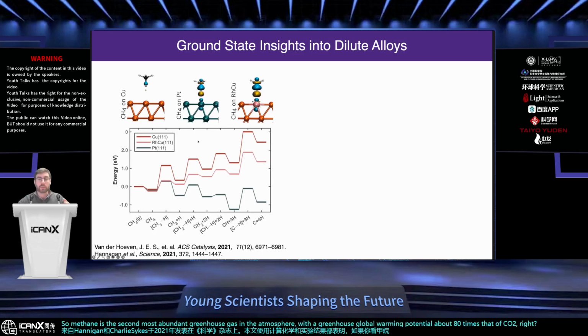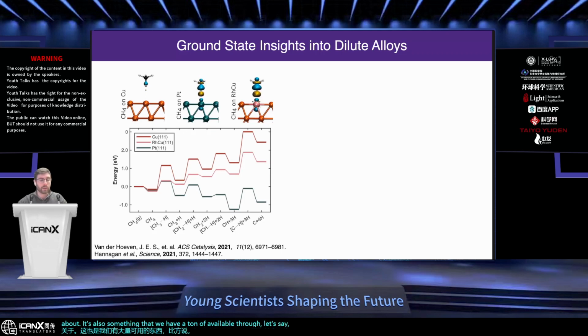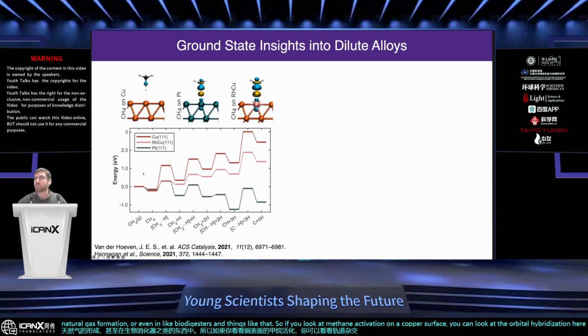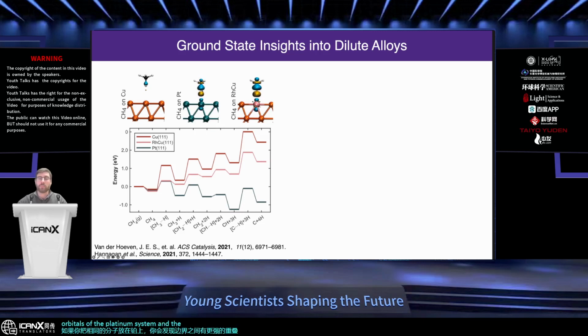It's also something that we have a ton of available through, let's say, natural gas formation, or even in like biodigesters and things like that. So if you look at methane activation on a copper surface, you can look at the orbital hybridization here and see that there's not really much activation in the system overall. If you put the same molecule on platinum, you see that there's a much stronger overlap between the frontier orbitals of the platinum system and the incoming methane molecule. But if you mix these two together and you have, let's say, rhodium in copper, now you get much stronger hybridization in the system overall.